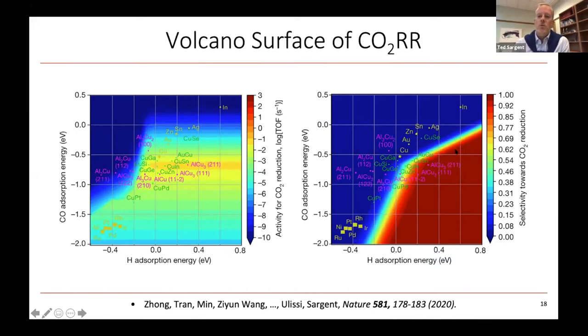But then if you also look for selectivity, which is what the heat map on the right is showing, and you prioritize that simultaneously with the activity for CO2 reduction, you'll see that you would like to have a positive or even greater than zero hydrogen adsorption energy to avoid the competing HER process. And so this does seem to point towards a hint that exploring the aluminum copper space might be an interesting area to explore.